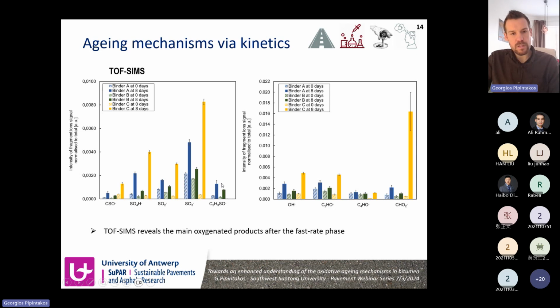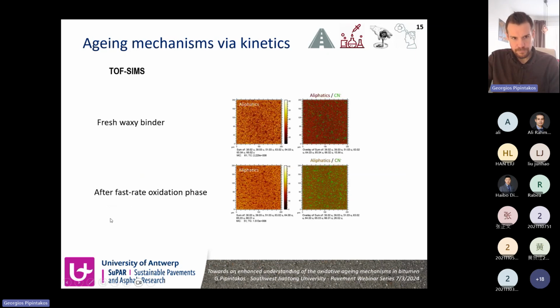Going to the results, it shows that we have an increase of all the sulfoxide containing fragments, which is in line with the hypothesis of sulfoxide formation, and also an increase of the hydroxide containing or oxygen containing fragments during the fast rate phase. So it was studied at 0 and 8 days, where 8 days is the completion of the fast rate phase. The second graph on the right also shows that we can have a formation of different types of OH containing fragments, and this can be not only carbonyls but also other types of chemical compounds like alcohols, which has also been hypothesized by other researchers in the past.